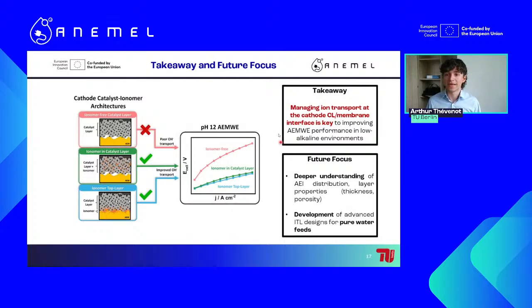This brings us to our main takeaway from this talk, which is that managing the ion transport at the cathode catalyst layer and membrane interface is key to improving your electrolyzer performance in low alkaline environments. Our future focus now would be to have a deeper understanding of the ionomer distribution and also of the layer properties after applying this ionomer, such as the thickness or the porosity, which can have a great impact on the performance increase. And then the development of advanced ionomer top layer design, this time for pure water feed. So this time with no OH- at all in your electrolyte.